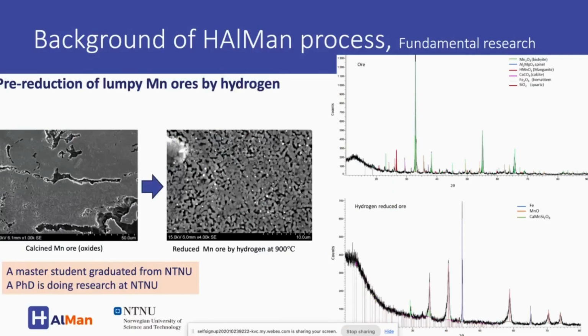On the right, you see two XRD spectra. The top one shows the ore before reduction, the raw ore. It has manganese in the form of bixbyite, Mn2O3, some calcite, CaCO3, and the iron is in the form of hematite. When we do the pre-reduction, we see the product is showing that all the iron is reduced to metallic iron, and manganese oxide to MnO, and we have some oxides left in the material, which are more amorphous or in minor quantity.